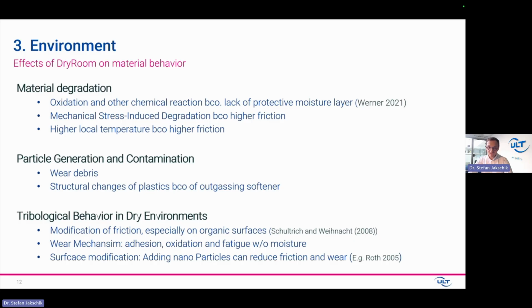And also the bad news here is you have the bigger particles which you can see, but this kind of material degradation also produces small particles which are barely visible or detectable. So when selecting the material for a dry room, special attention needs to be taken on what kind of material you use in order to minimize these kinds of effects here.